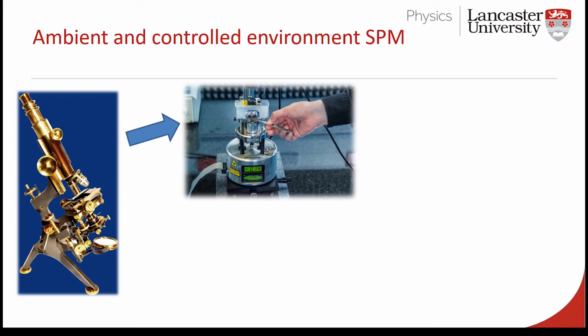So don't worry too much about the way the AFM works. But the snapshot of it is that we take an atomically sharp probe, a very sharp probe, and we scan it over the surface of our material. And we measure the mechanical interactions between that probe and the substrate, between our sample and the probe. And depending on how the probe moves, we can detect that motion, we can detect torsion, we can put electrical current across it so we can measure the electrical characteristics, we can put heat across it and measure the thermal characteristics. But we can map with extremely high resolution the structures and properties of our samples.